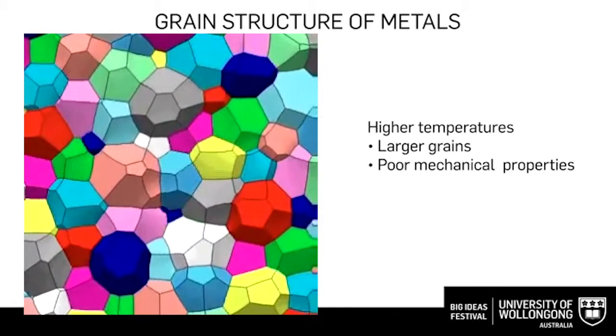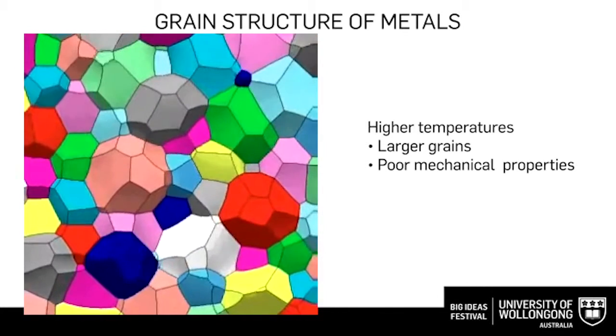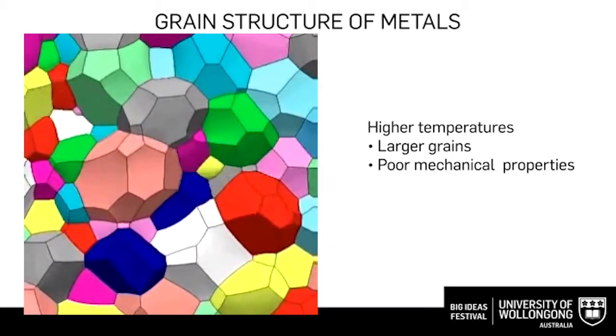Unfortunately, this grain structure usually develops during the solidification stage of the material. So once we melt it and it re-solidifies to form solid, the grain structure is formed. And once it's there, it's very difficult to refine it, almost impossible. Unfortunately, as things go, we can't refine it easily, but it's very easy to get the grains to grow. And from a metallurgical point of view, that is what we don't want. We want the grains as small as possible.